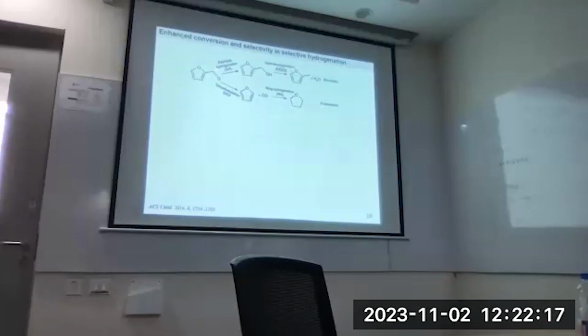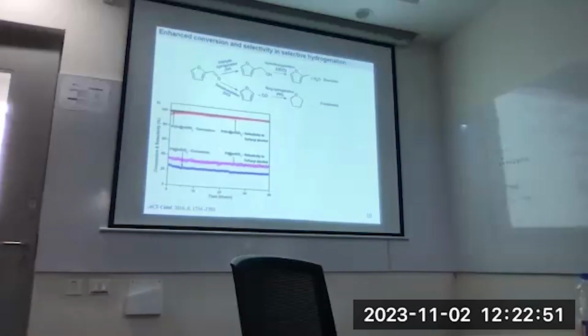You don't want, for this particular compound on platinum or nickel, it can be fully hydrogenated. All the bonds can be hydrogenated very easily if you use just nickel or platinum. It's just going to adsorb flat on the surface of the platinum or the nickel nanoparticle. And all the bonds that are possible to be hydrogenated will be hydrogenated. But if we make this platinum tin, we restrict the mode of adsorption of this particular molecule on the surface of the catalyst, right? So we want only this. We don't want these other compounds. We can get these other compounds with other catalysts if we want to. But for the purpose of my work, we only want to make this, right? So this is platinum tin.